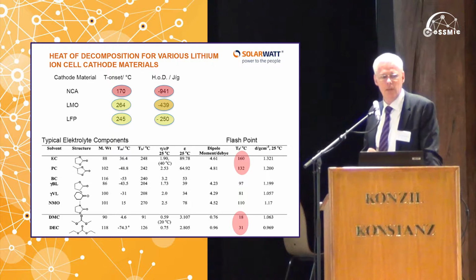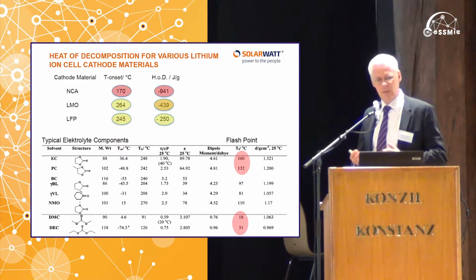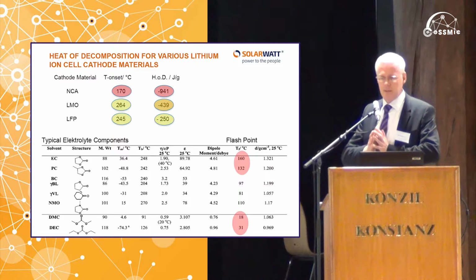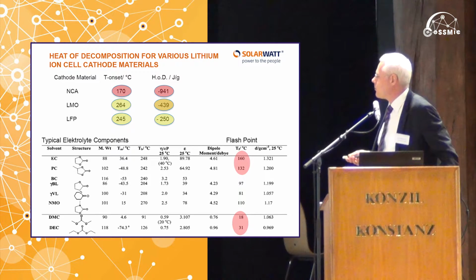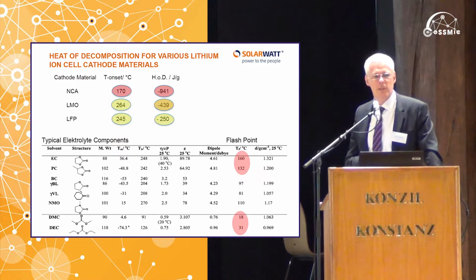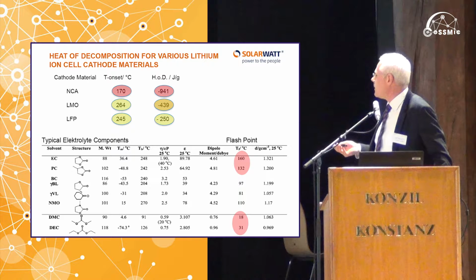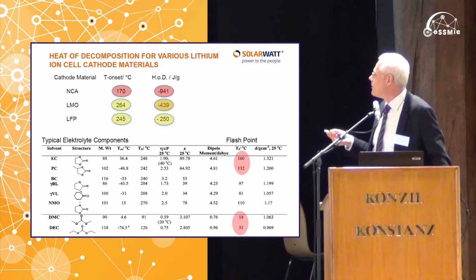But the point is that failure of a battery starts with evaporation of the electrolyte, not with decomposition of the cathode. The first thing to happen is that the electrolyte is decomposing, and then you have electrolyte vapor pressure building up inside the cell. And the next thing is that the cell opens and the vapor comes out of the cell, and then you have a mixture of different electrolyte components, some typical components are shown here, and they have flash points which are far below the temperatures at which the cathode starts to ignite, so to say. So the first thing is that the electrolyte ignites, and this electrolyte is more or less the same in all of these battery technologies. So forget about these different temperatures. The interesting thing is the flash point of the electrolyte.